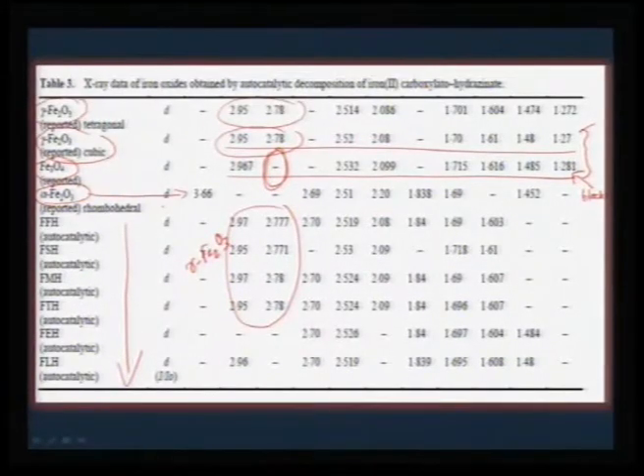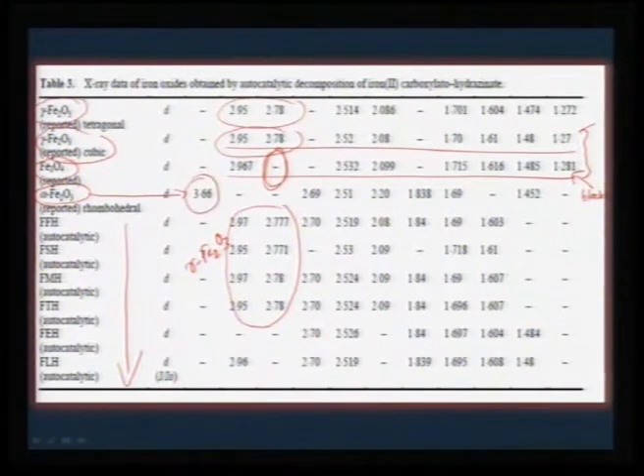If you need the high-temperature phase, you need to use a different precursor altogether. If you transform to very high temperature, you will lose the property — alpha Fe2O3 comes in, distinguished by a peak at 3.66 Å. Once you know that, you can understand that part of your gamma Fe2O3 has transformed into alpha. This is an example where a phase can only be stabilized at low temperature, for which you need to take a corresponding precursor. Not all precursors necessarily give the high-temperature phase, so you need a mechanism to control the exothermicity.